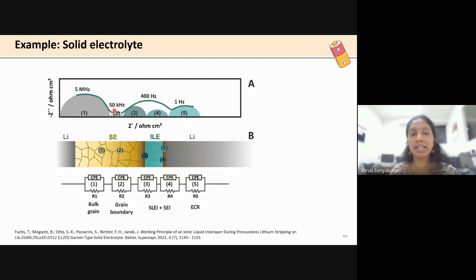I can similarly associate these with, I can also prepare a control experiment. So I know that this bulk grain is coming here, and I do not know what is going to happen with these other semicircles. Over here, I will again do a control experiment. I will prepare a cell with lithium, solid electrolyte, and lithium, and then run an impedance. And when I do that, I will notice that there is this component alone and all these three semicircles are not there. When I know that, I will definitely be able to find out that the second semicircle is coming from the grain boundary, and that's how I associate it with the grain boundary resistance. Similarly, all these electrolytes can be controlled in another system, and their values and their frequency ranges associated with their omega max can be compared, and we'll be able to see how the entire spectrum is evolving, and based on the different phenomena, we'll be able to correlate what's happening.